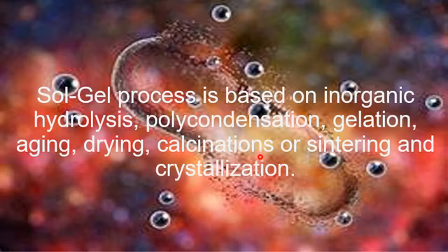Like for ferrite, the minimum threshold usually used for production of a nanoparticle of ferrite is between 800 degrees centigrade and 900 degrees centigrade. So this calcination and sintering temperature is very important for getting a single phase material.